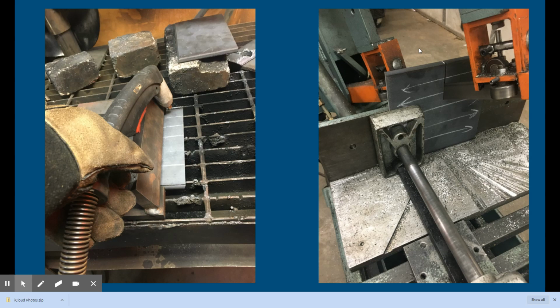We cut our coupons in-house and do everything in-house, but it is important to make sure you do it the right way. If you don't have a bandsaw that tilts at an angle, you can do alternative methods of cutting. So I created this jig for cutting with our handheld plasma cutter. And this one sets it up at a 22.5-degree angle. I just take my other hand, and pinch it right here with my thumb on top of this piece of cold rolled, and I'll just simply slide it all the way down. It takes a little bit of practice, but honestly, if you get good at it, you can cut coupons way faster than you can on the bandsaw.